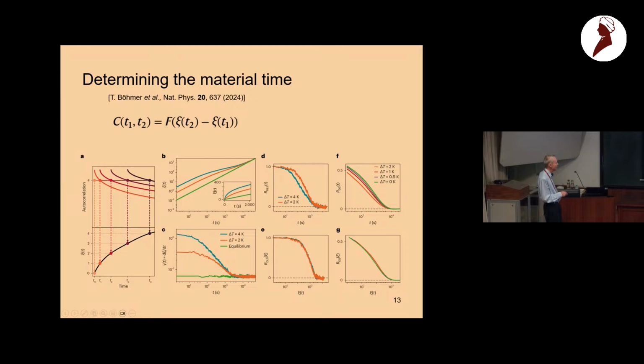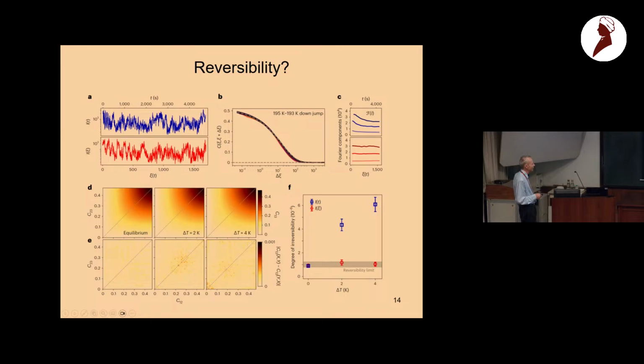So these are for some jumps, and of course, they jump to the temperature. Eventually, they will end up following the green line of the equilibrium temperature. I don't want to go through all the curves here. Here are some normalized relaxation functions for the light scattering itself, and here for a dielectric signal for different jumps, and as function of time, and they should then collapse if we do it as function of material time, and it seems to work pretty well. This is actually the first time that the material time has ever been measured, because it's really very demanding to do this. But coming back to the title, reversibility.